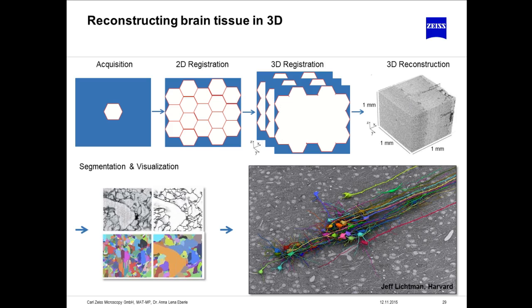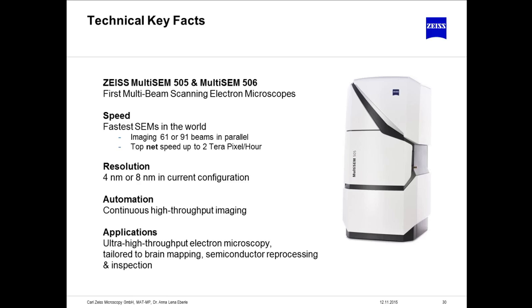By now, the largest data sets that are reconstructed are maybe in the tens of microns cubed range. I think the largest data set I've heard of is about 350 microns cubic. And this was, I think, taken at a larger pixel size. So again, this is really a challenge that needs to be solved. And maybe the multi-SEM in the end might be one of the drivers to pace this research up a little bit, as here the amount of data is just orders of magnitude higher.